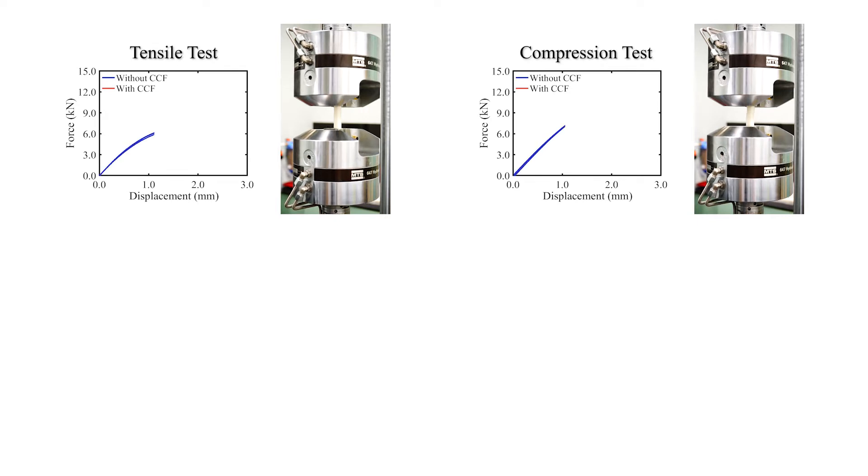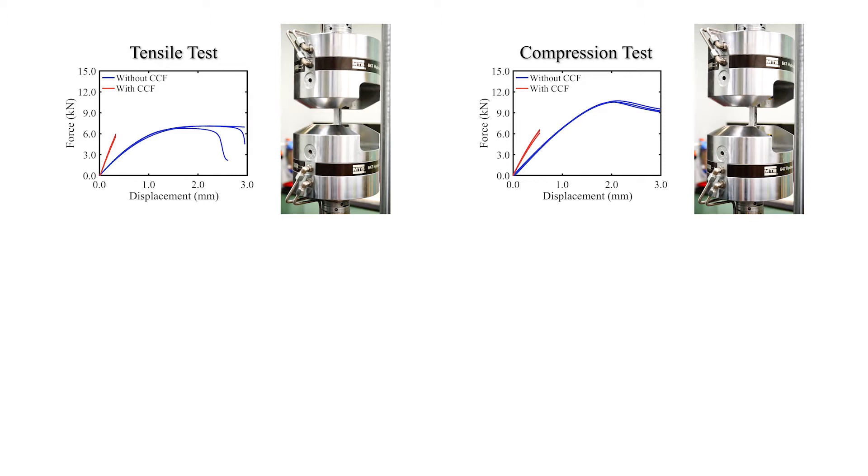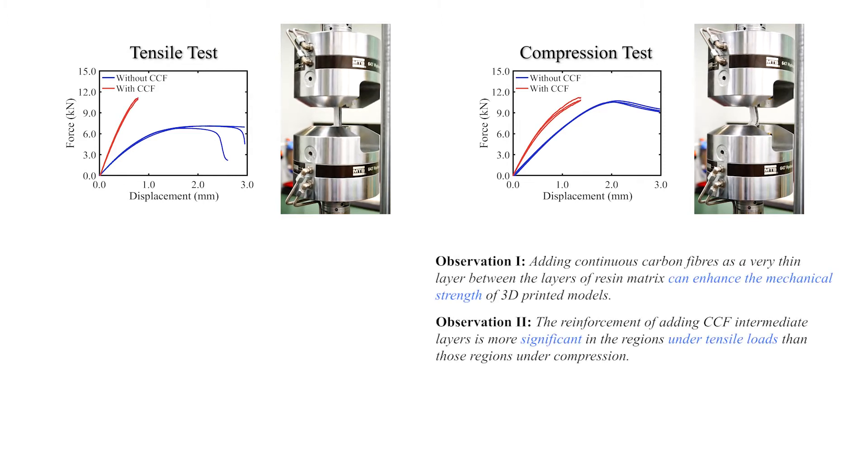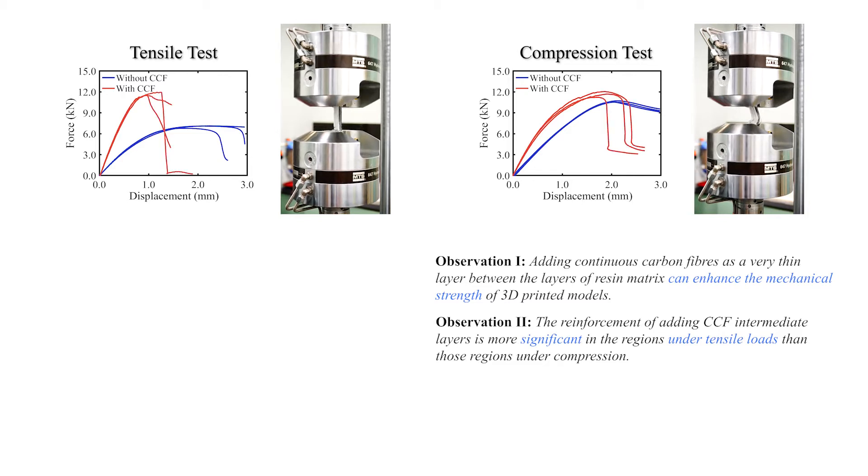Considering the anisotropy of continuous carbon fiber, we first conduct two experiments to study the mechanical behavior of models with or without carbon fiber under tensile and compression loads. The experiment shows that adding continuous carbon fibers can enhance the mechanical strength, especially under tensile loads.